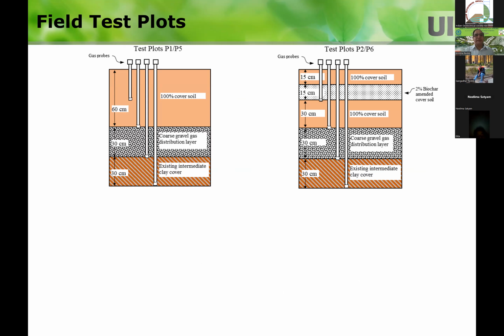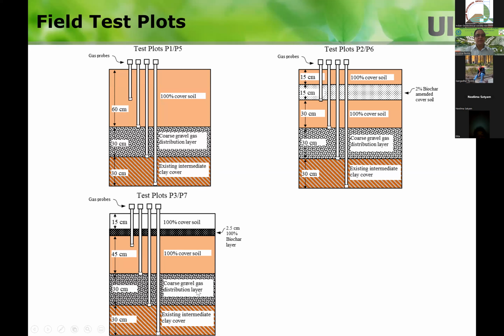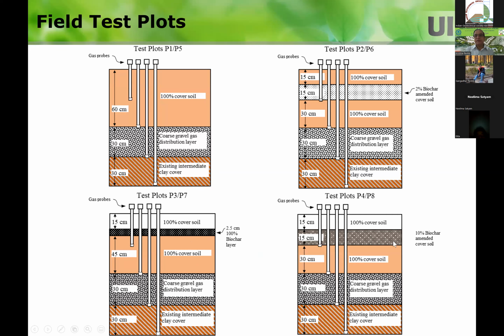So we went to the field and we did the test plots. So in this case, you have an existing intermediate clay layer, a coarse gas, and then you have a 100% cover soil. This is like a baseline. And then we put the biochar, 2% biochar amended soil layer. And here we put a layer of biochar, and here we put a 10% amended biochar. So basically, we try to create different profiles in the field.